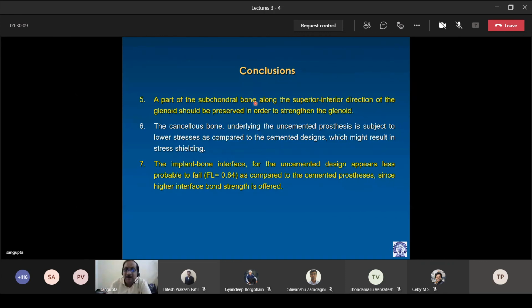The higher the density, the higher the strength offered by the bone, and thereby the lesser the chances of interface failure. Okay, the cancellous bone underlying the uncemented prosthesis is subjected to lower stresses as compared to the cemented design, which might result in stress shielding. That we have already seen, as I presented the results in the form of pictures or figures. But a very important revelation comes when we play with the numbers. In the case of the uncemented prosthesis, there is no cement here. The implant bone interface for the uncemented design appears less probable to fail. The highest FL value that came out for the implant bone interface in the uncemented prosthesis is 0.84